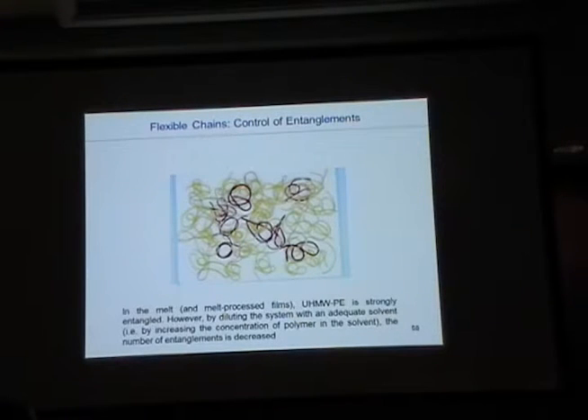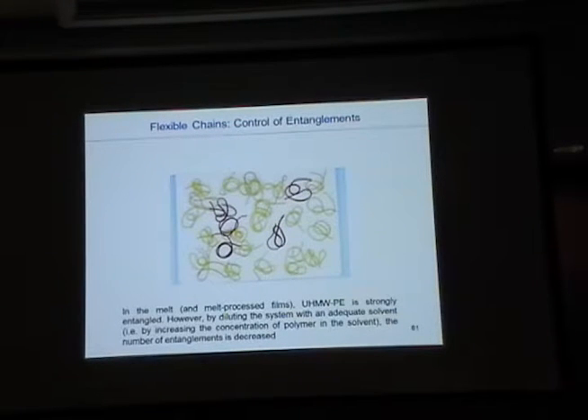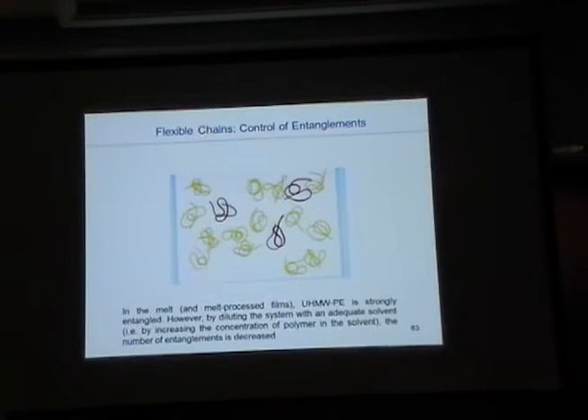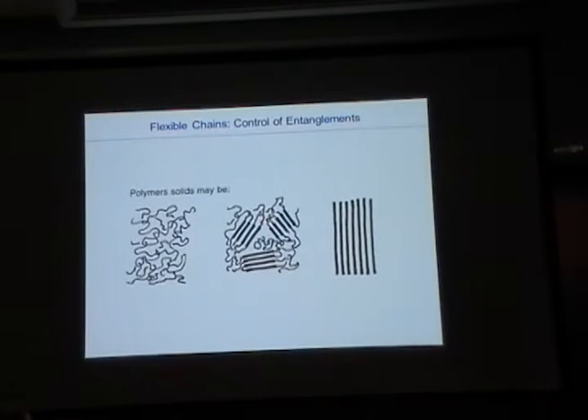At a certain moment of time, we don't want to over-dilute. You still have a network, so most of the red chains are connected, so film forming is still good. However, you reduce sufficiently the amount of entanglement, so the material can, at least to a certain extent, crystallize. If it goes too fast, you start to have these unconnected molecules, and they will lead to crystals if you're lucky, but it will really prevent film forming.